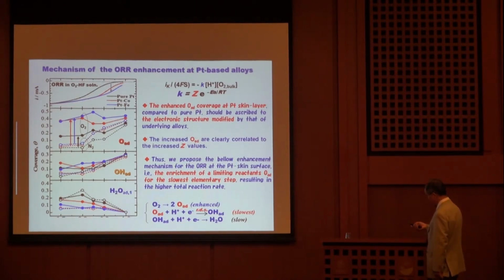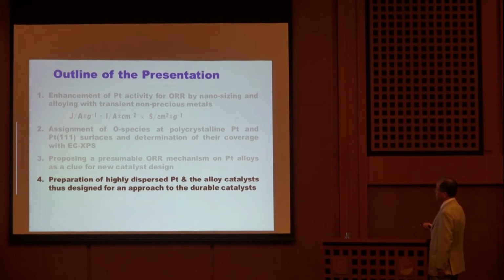That is enrichment of the limiting reactant O species for the slowest elementary step, resulting in the higher total reaction rate. Now, we have discussed the mechanism of the enhancement by alloying platinum with non-precious metal. Now, we try to prepare practically usable, highly dispersed platinum and alloy catalysts, thus designed for an approach to the durable catalyst.